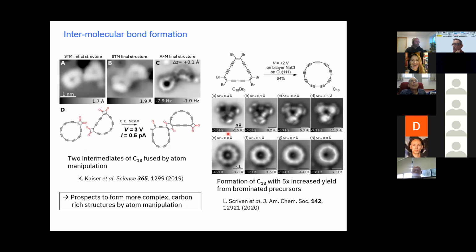We found the molecule also interesting as it allows us to also do further on-surface reactions. I told you, you cannot make the molecule that's so very reactive, but we can also exploit this reactivity in the plane if we bring precursors close together. And this we did here. So here we have 2 of these precursors. Some of the masking groups have already been dissociated in these 2. And now by applying 3 volts above them, we actually fuse them and form this ring between them, and have now fused these 2 carbons. So this might be useful to make other carbon-rich designer structures.